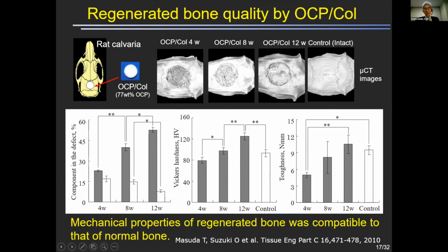And also we investigated the hardness of the regenerated bone. Because hardness will increase gradually, and the toughness, fracture toughness also increased, approaching the intact normal bone. So this means that the regenerated bone induced by OCP collagen has a similar property in terms of mechanical property.